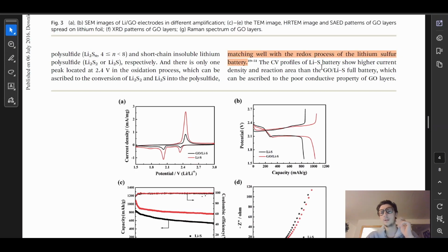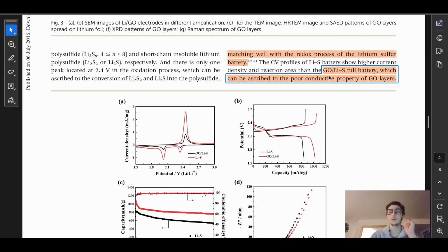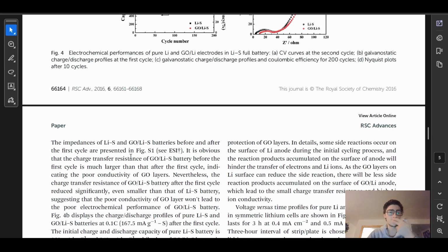The CV profiles of lithium sulfur batteries show higher current density and reaction area than the graphene oxide/lithium sulfur full battery, which can be ascribed to the poor conductive property of the GO layers. Okay. But they said graphene had good ionic conductivity, and here their data is showing that it doesn't have good conductivity. Maybe it has good ionic conductivity, but poor electrical conductivity. I don't know if there's a difference. I'm just kind of positing.